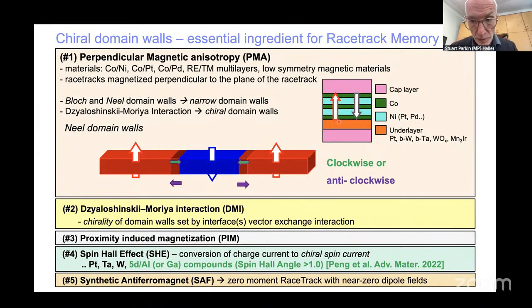So the interface with platinum does two things. It creates anisotropy. It creates this very interesting exchange interaction. At the same time, there's a proximity-induced magnetization in the platinum. The platinum becomes slightly magnetic. It turns out that's very important. It can be giant. The neighboring platinum moments have a magnetic moment of about 1 Bohr magneton. And the platinum layer also gives rise to the spin Hall effect, converting charge current to a chiral spin current.